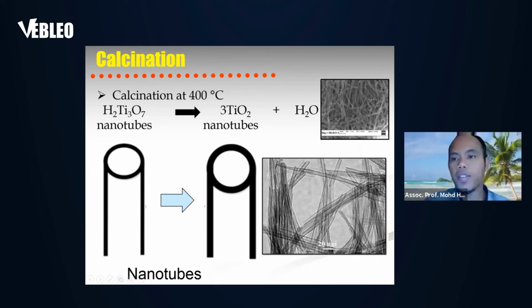Therefore, we can see very nice elongated nanotubes, and then to prove the formation of the titanium dioxide nanotubes, we use TEM, transmission electron microscope, and again we can see very nice hollow elongated nanostructures here to confirm the formation of titanium dioxide nanotubes.